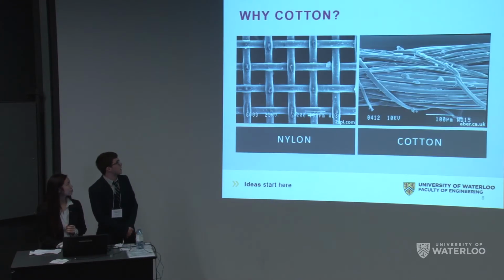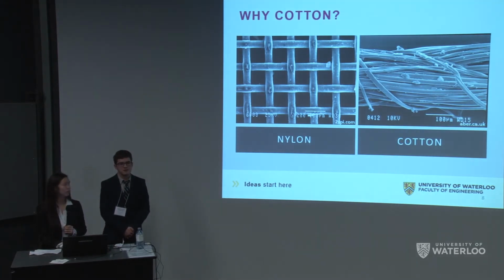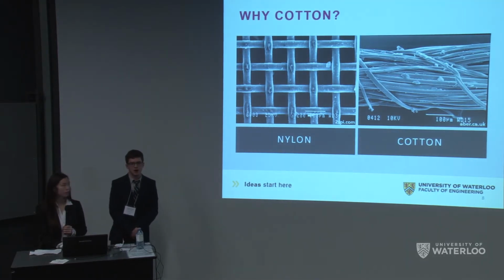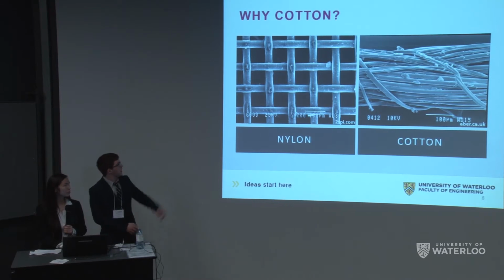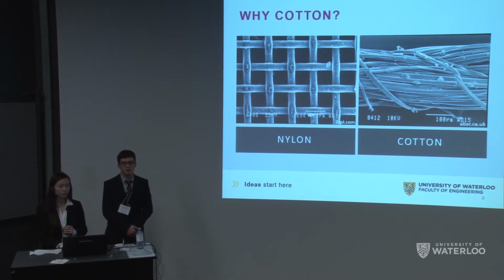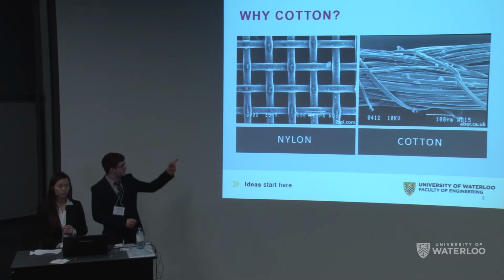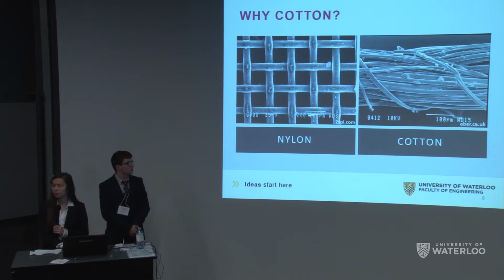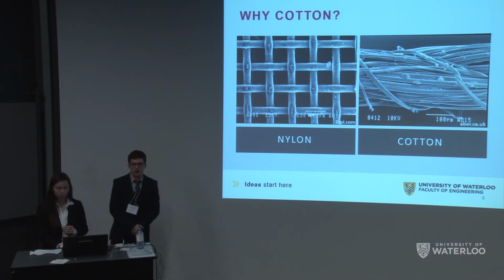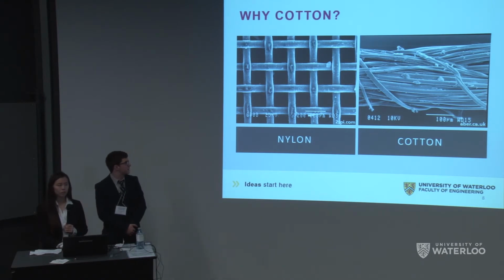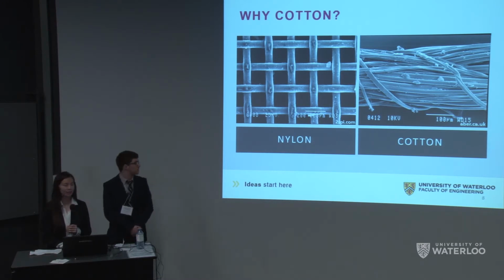So let's take a look at why we chose to use cotton. The main reason for cotton is its morphology. Cotton is composed of multiple fibrils, and in the image on the right you can see one such fibril as the large structure, and it's composed of multiple microfibrils, which are the small threads shown throughout. This gives it a high surface area, allowing for many van der Waals interactions, and as a result you get strong adhesion for your deposited material. This can be compared to other materials that are used for textiles, for example, nylon. Nylon has a much lower surface area, and as a result has worse adhesion.